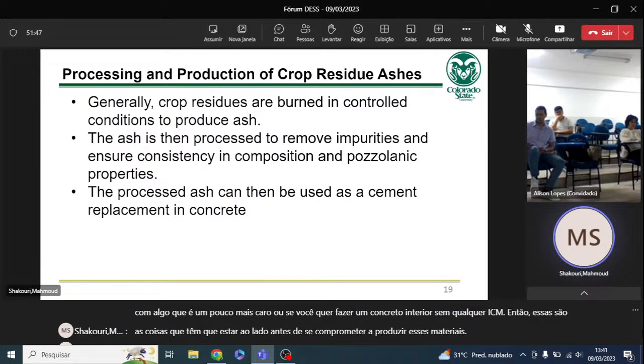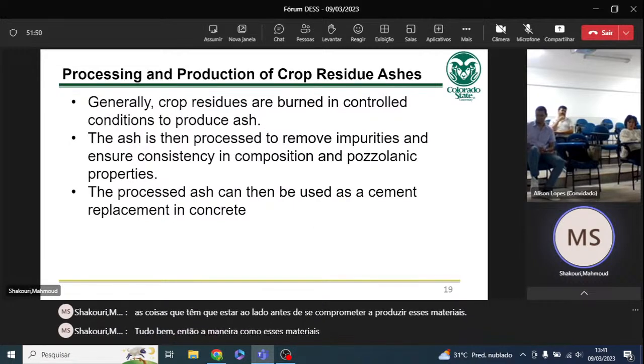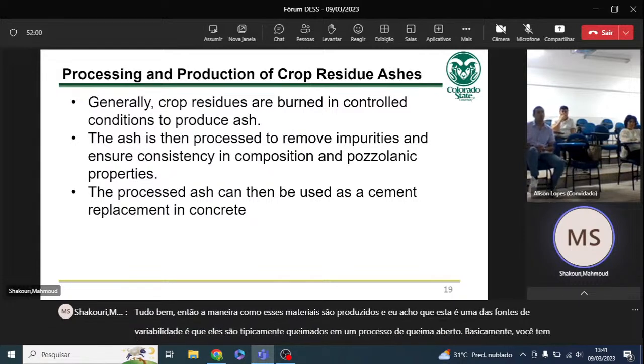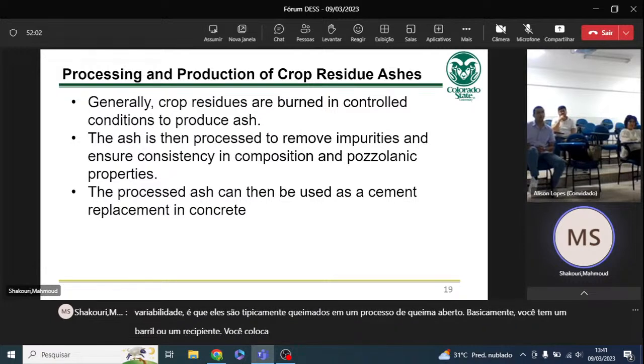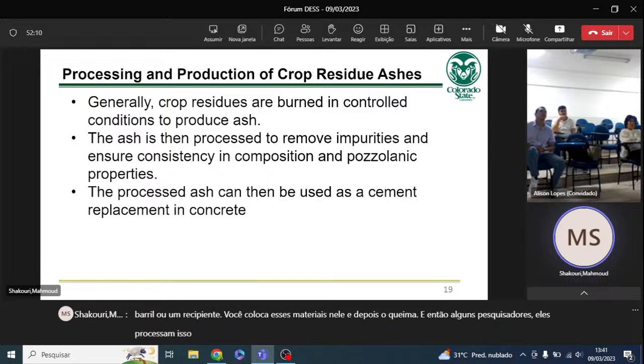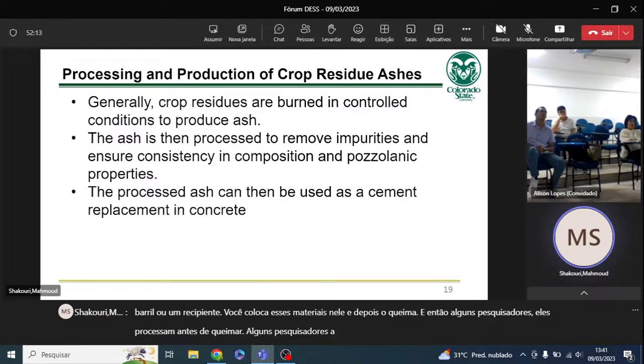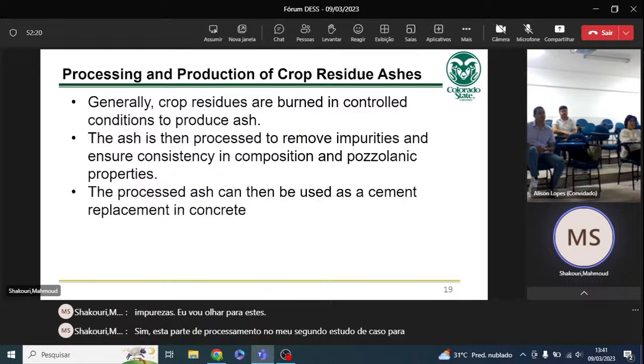All right. So the way that these materials are produced, and I think this is one of the sources of variability, is that they are typically burned in an open burning process. Basically, you have a barrel or a container, you put these materials in it, and then you burn it. And then some researchers process it before burning. Some researchers process it after burning to remove some of the impurities. I'm going to look at this processing part in my second case study to see how it will affect the properties of your ashes.